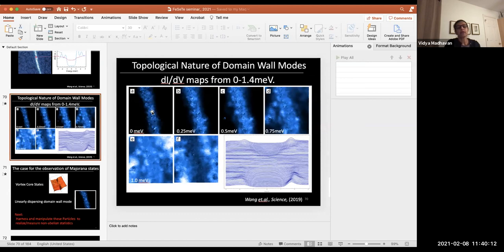One thing I would say is if you went to this point and you measured dI/dV, you can actually see it in the spectrum. These spectra, the completely flat density of states, is obviously right in the middle, because that's where all these states coexist. But if you went slightly off, you can see that these states don't exist, and these will show up as two little bumps. And when you go slightly even further off, those go further out in energy. You can see all those little details in our spectra. So you would have to capture all that in the odd frequency scenario.